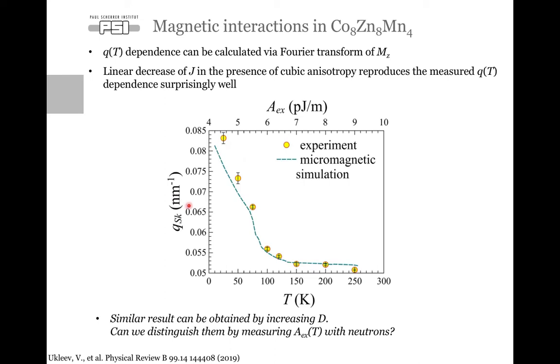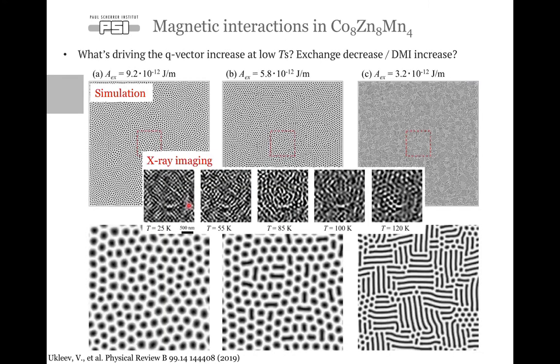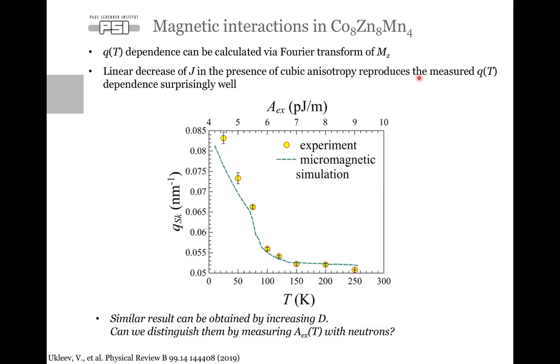But in fact, in this simulation, we couldn't really distinguish between the influences of the exchange interaction change and the Dzyaloshinskii-Moriya change, because we could either change exchange stiffness linearly or the Dzyaloshinskii-Moriya parameter and obtain the same results, because they equally contribute to the spiral or Skyrmion lattice parameter.